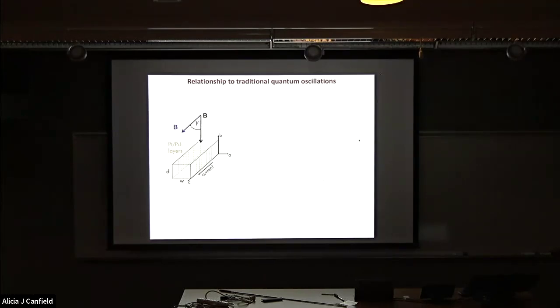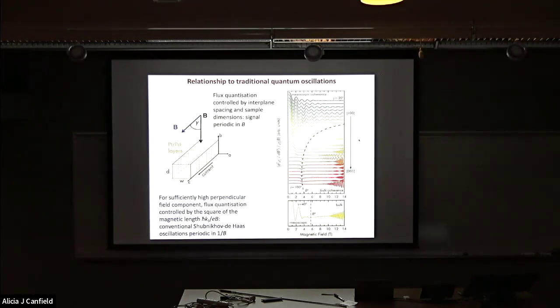You take the field away from being perpendicular to the plane, to rotate it to be in the plane. And you see something which is, I would say, physically so cool. What you see is that the field periodic oscillations that you have when the flux loop is determined by the dimensions of the material change to inverse field periodic oscillations when the flux loop is controlled by the magnetic length. So I personally, even though I'd worked under Shoenberg, I'd never really fully intuitively understood why this reciprocal field periodicity happened. Well, this certainly tells you why. And you can even see it as a function of field at some angles going from one regime to the other if you've got things tuned right with your samples. So, yeah, I understood a lot.